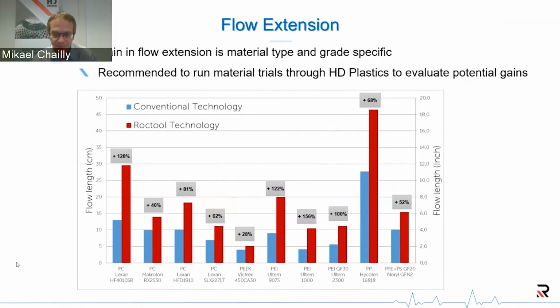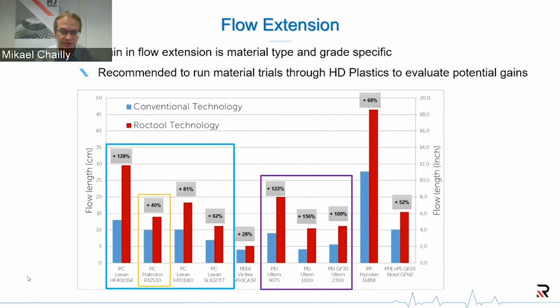And if we consider a broader view, we can see that if we change the material type, let's say from PC up to, and we compare that to the PEI family, we can see that the gains are not the same. As an average on the PC family, we can say we are about 75% in terms of flow length improvement with the material. On the PEI, which is a much more viscous material, the flow length absolute value is of course less because of the viscosity of the material, but the gain is more like in the 125% range.